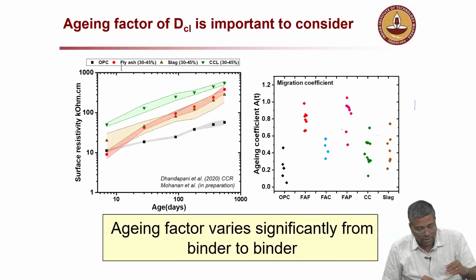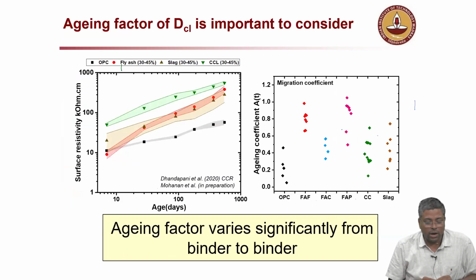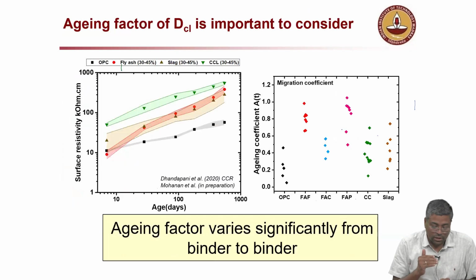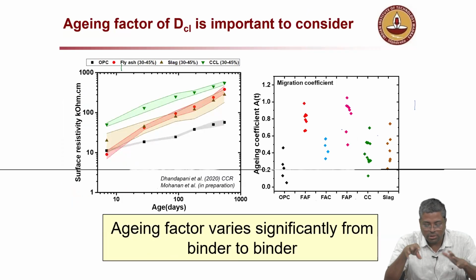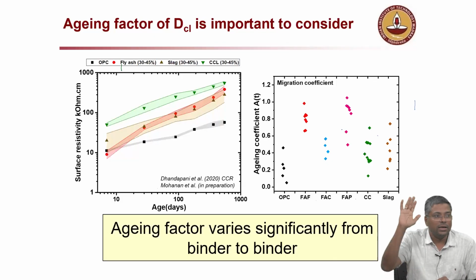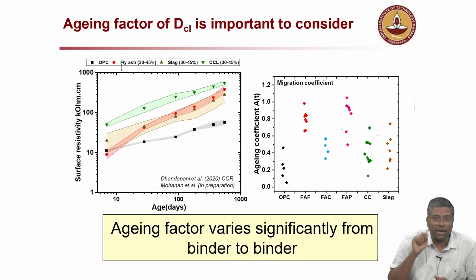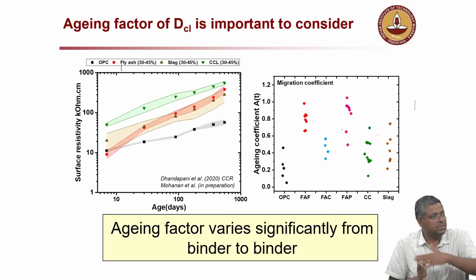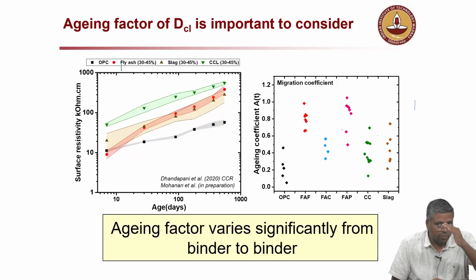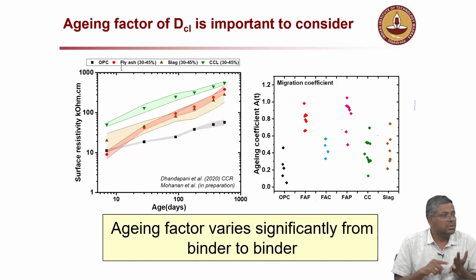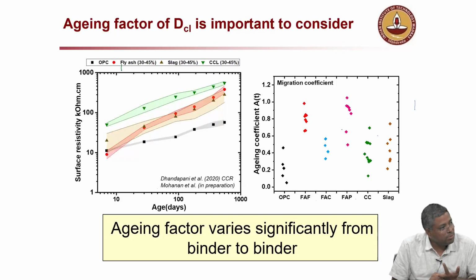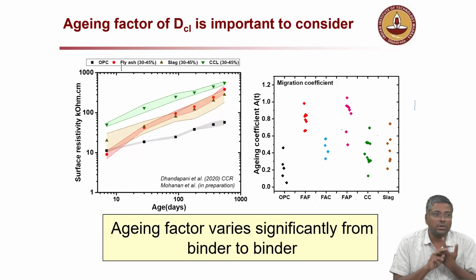Okay. Now you can see here on the y-axis you have resistivity. On the x-axis you have time. Now what does this essentially show? The resistivity is increasing for the green, orange, red colors, all that, right? Fly ash, slag, and calcined clay cement, limestone system, and the gray one over there is the OPC. Very clearly, the rate is very less. The gray one, the slope is much smaller than the other ones. What does it mean? When you talk about fly ash or slag systems, over a period of time, you can really have high strength and better durability parameters.